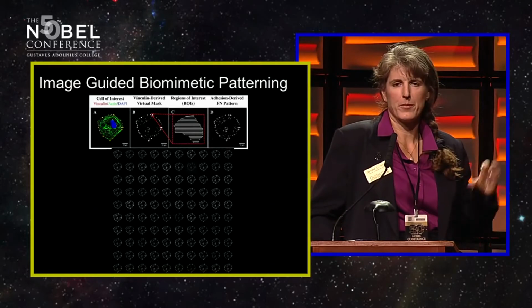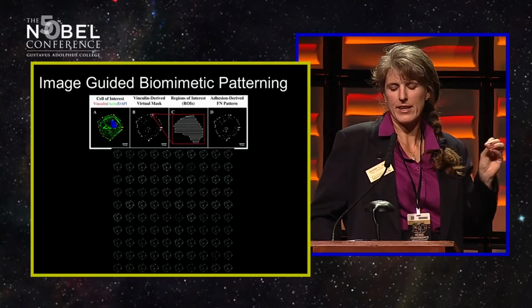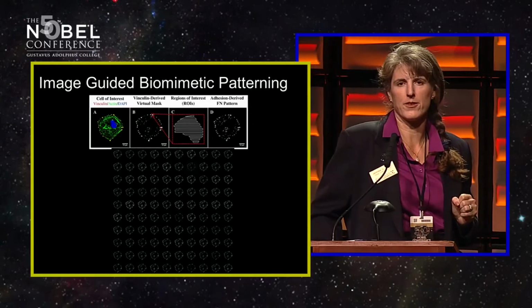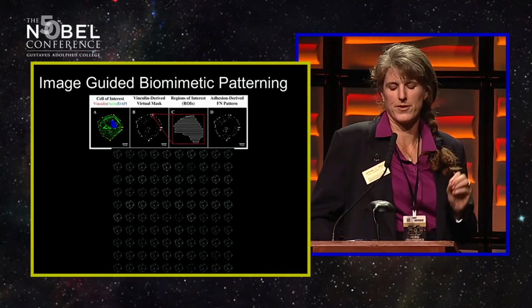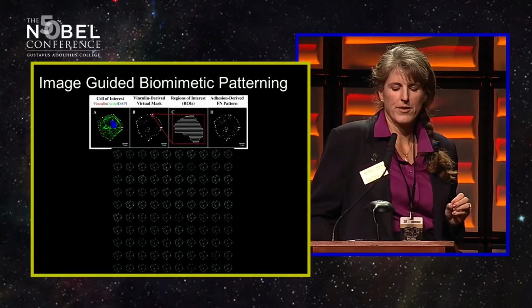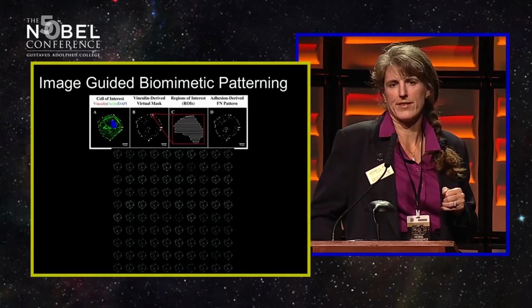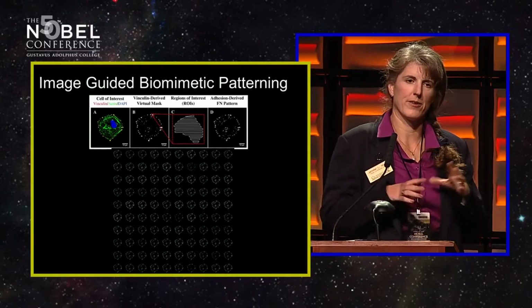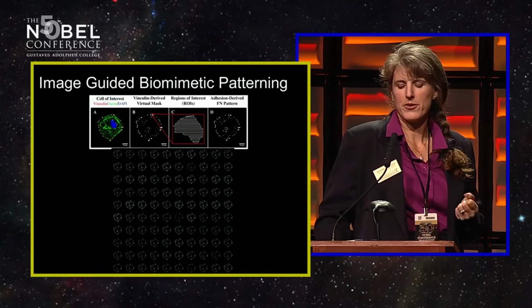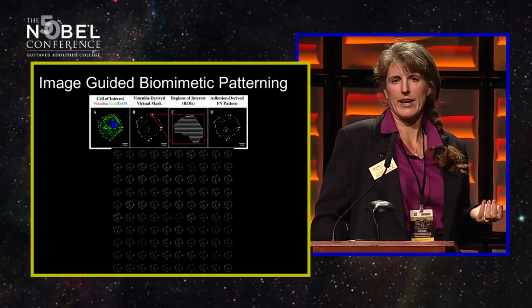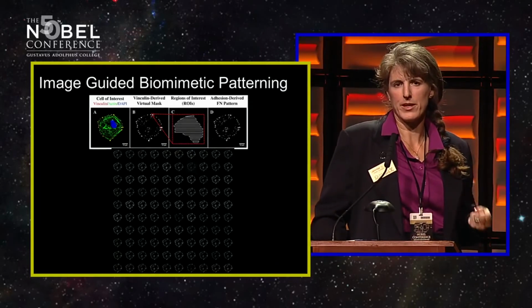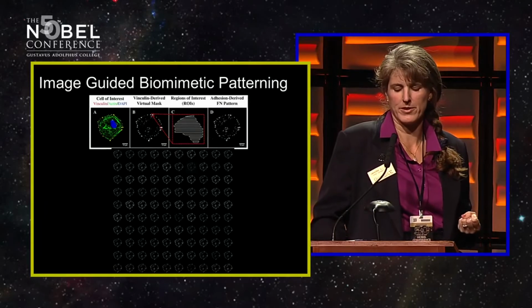And then we end up cross-linking in the adhesive ligands for the cells just in those regions where we expose to the laser light. When we do this, we end up with a pattern that the cells can interact with, where instead of being random geometry, we're looking at whether or not we can guide new cells to adopt the same type of phenotype as the original cell of interest.